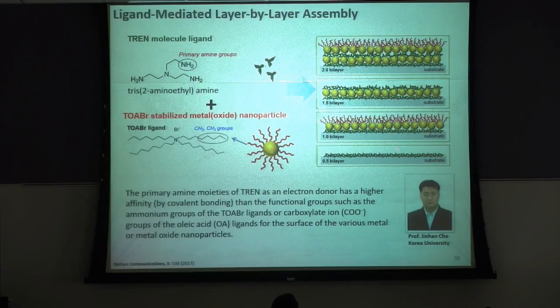So we move to the nanoparticle solution. Then this primary amine group has a stronger affinity than this ammonium group. So this primary amine group can detach the ammonium group and adsorb on the surface of this gold nanoparticle. So basically, we can generate a gold nanoparticle layer on the surface of the substrate.